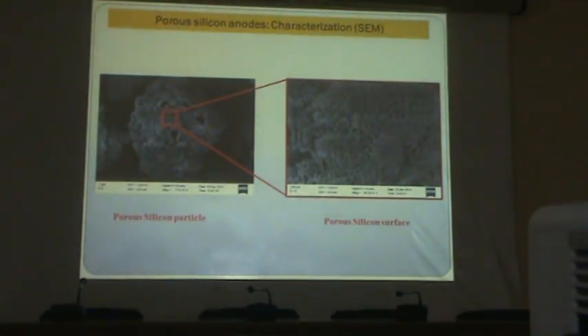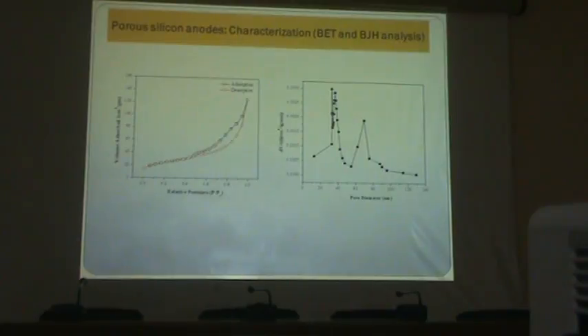And this was the pore structure which I already showed. If you see, the porosity is around 10 nanometers, maybe up to 100 nanometers. We did a surface BET characterization and used BJH type analysis. The surface area was around 80 to 90 meters squared per gram. Then the pore diameter, like you asked, is around 20 to 40 nanometers, and some of the bigger pores are around 60 to 80, mostly in this range.